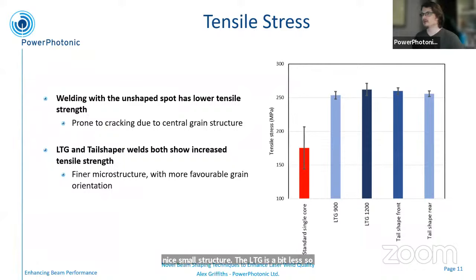We then run tensile stress measurements, so testing these to their breaking point. The weld with the unshaped single core spot has a tensile stress of about 175 megapascals, whereas for all of our shaped beams, we achieve over 250. So the finer microstructure is actually providing a stronger weld.